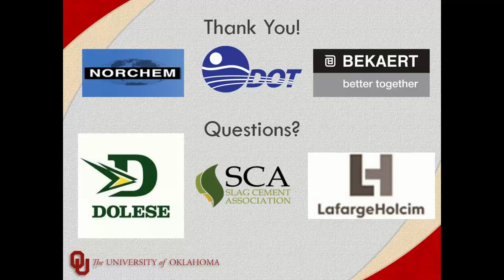And it looks like we have one more question that just popped in. Were you able to achieve the FHA objectives as far as the compressive strength at 21.7 KSI? I always hesitate to answer this question because I have no proof, but I have done it. And it was a random mix. I've done a lot of test batches with this, not really changing anything, just monitoring our materials. A lot of times when we switch bags of the supplementary cementitious materials, silica fume and the slag, or when we get a new batch of type 1, I'll try different things. I'll try other mixes, but I have actually gotten it. I've gotten J3 to hit about 22 KSI, almost 23 once.